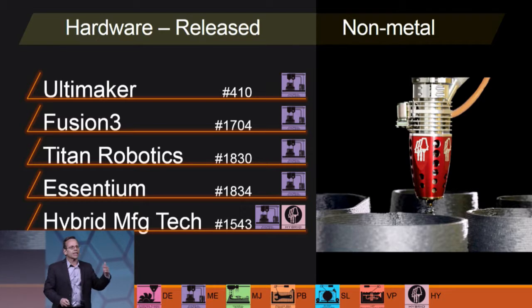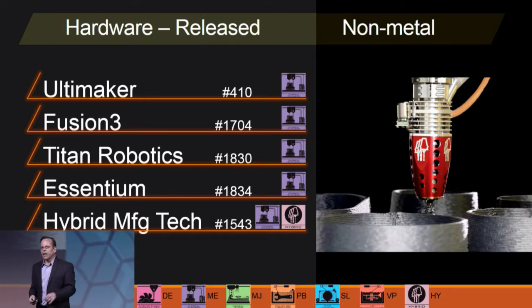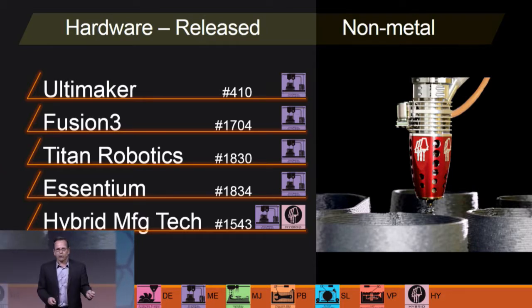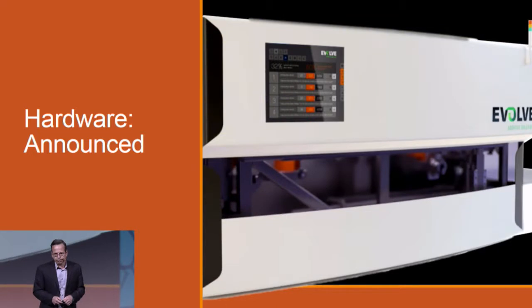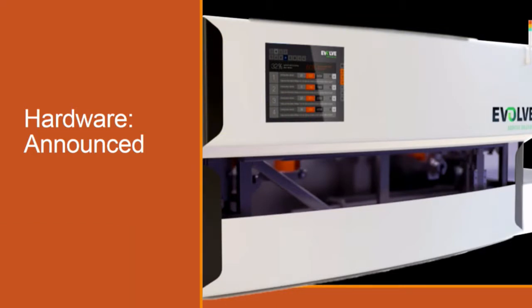Previously, it's focused on the directed energy deposition technologies or laser metal deposition. Now it's into polymer extrusion. This is pellet fed and pumping out upwards of 20 pounds of material an hour. So we're going to kick over into what's been announced but not available. So we're getting a little peek into the future.